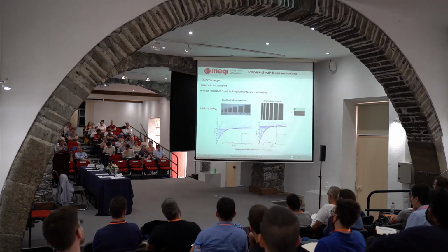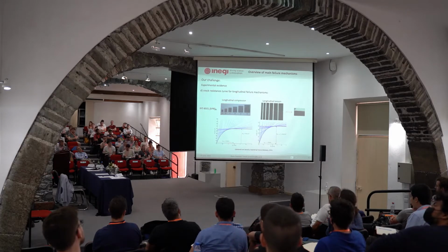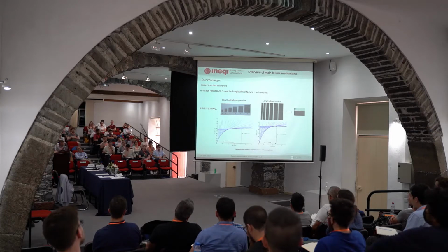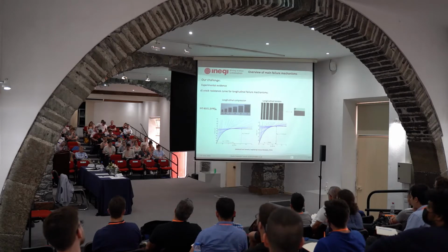So we had to solve this problem, and what we did was come up with a methodology where we relate size effects with the R curves. We test up to failure different specimens, in this case with two edge notches in tension and compression, and from the size effect law we can get the crack resistance curve. But the bottom line here is that you do get this R curve, and again, the analysis models need to account for the different energy dissipation mechanisms that result in these R curves.